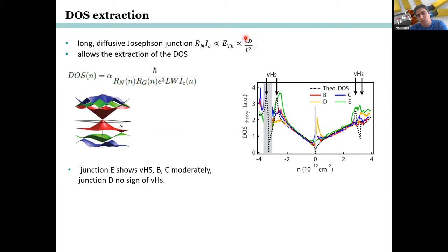Now, why is this interesting for us? Because the diffusion constant is connected by the Einstein relation to the density of states. So if you are able to measure the normal state resistance and the critical current at the same time, then with this equation, you can get the density of states just from normal state and critical current measurements. And this is such